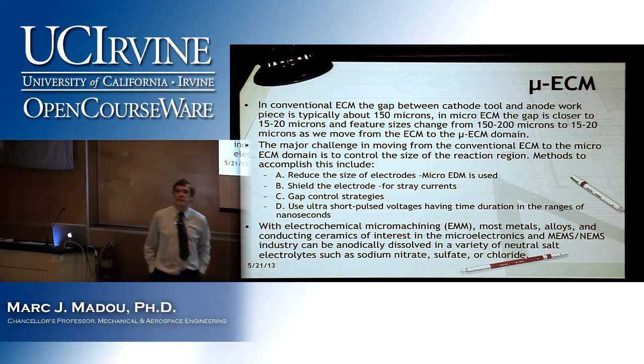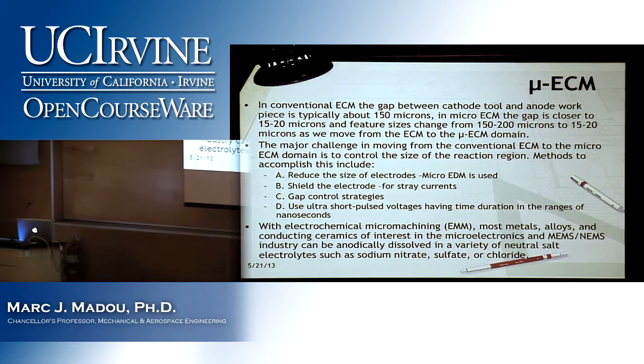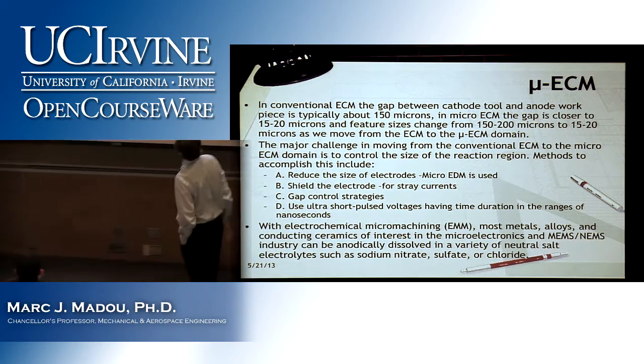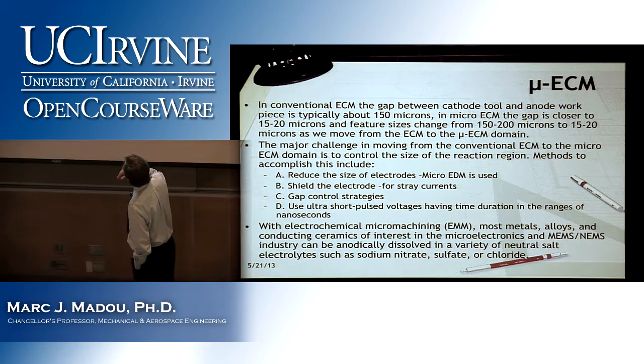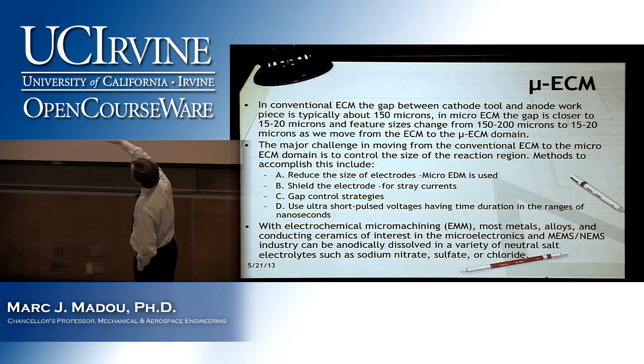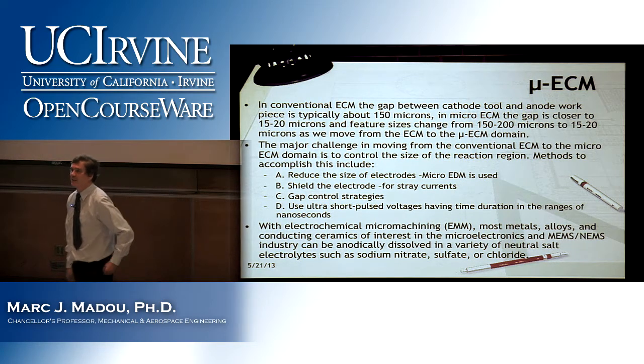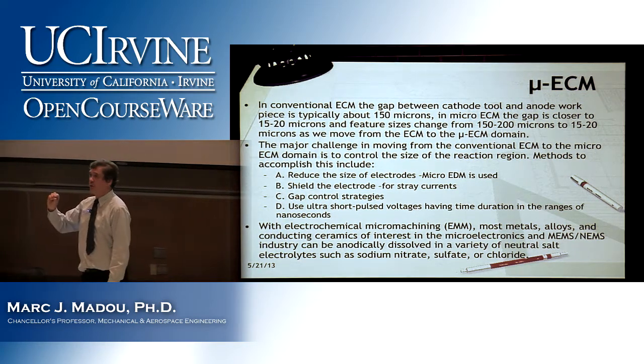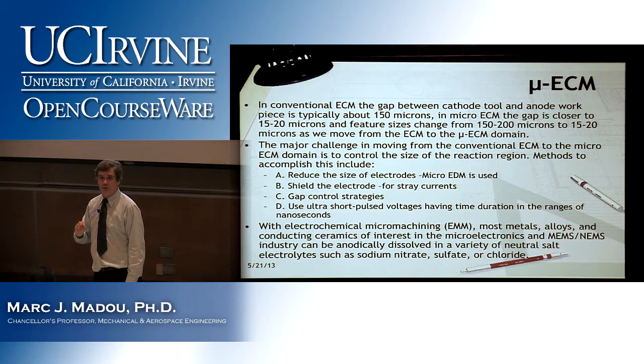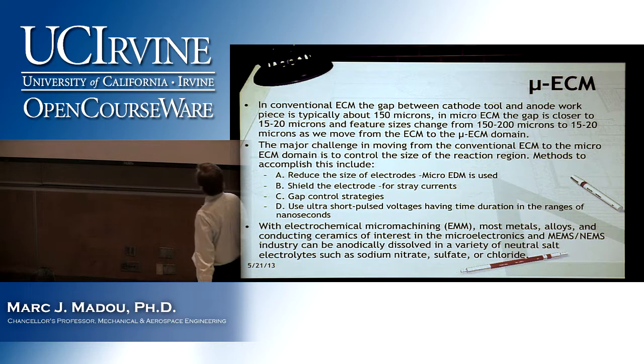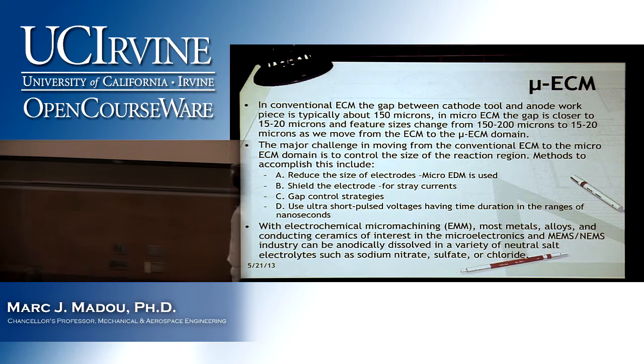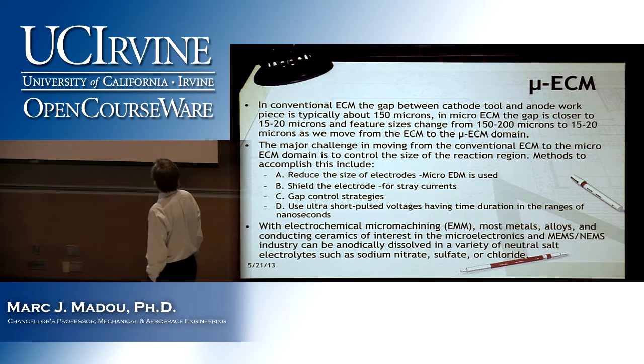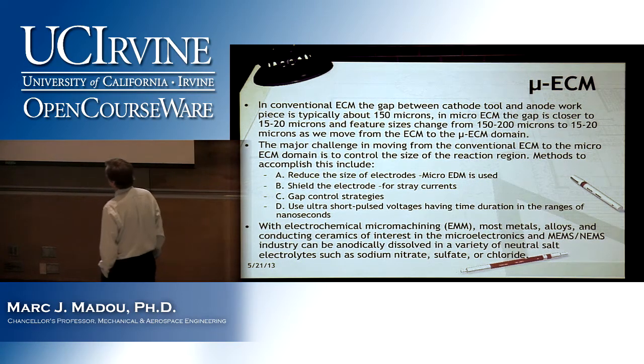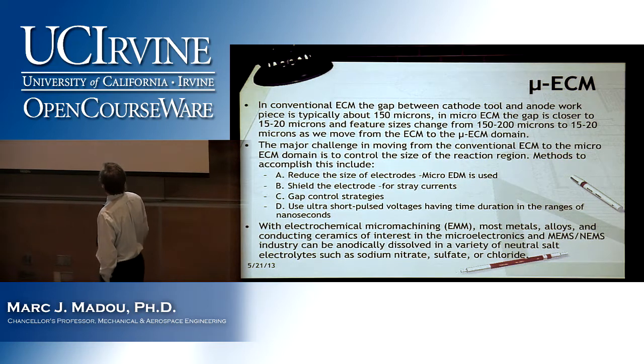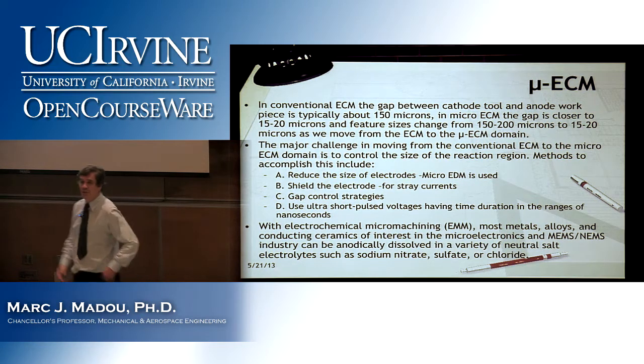What are the differences between the two? Well, number one, in conventional ECM, the gap between the cathode tool and anode workpiece is about 150 microns. In micro ECM, it's more like 15 to 20 microns. That makes sense, right? It's much smaller tool, so you can bring it much closer to the surface. It's about 10 times smaller. Now, the major challenge in moving from conventional ECM to micro ECM domain is to control the size of the reaction regime. And we saw that already, right?